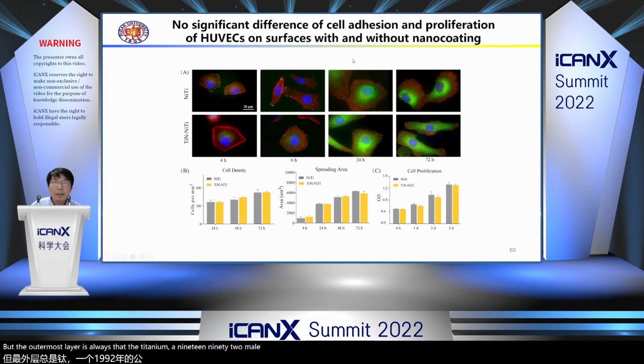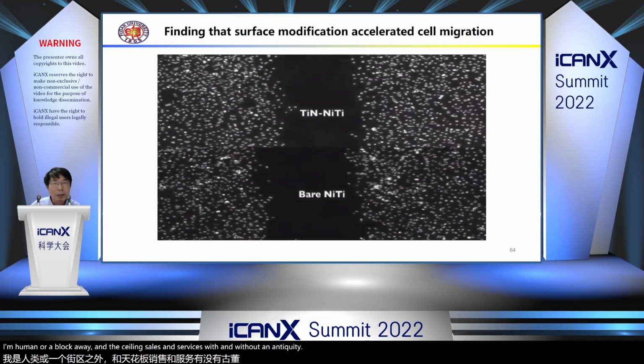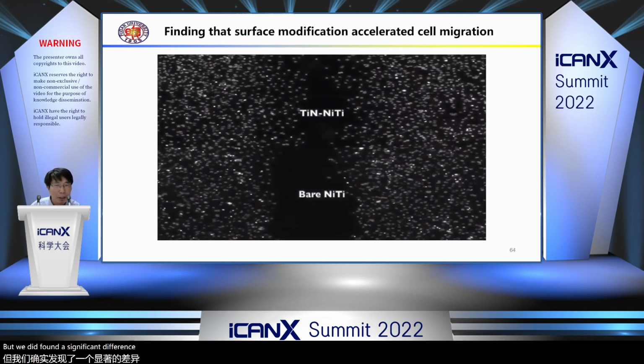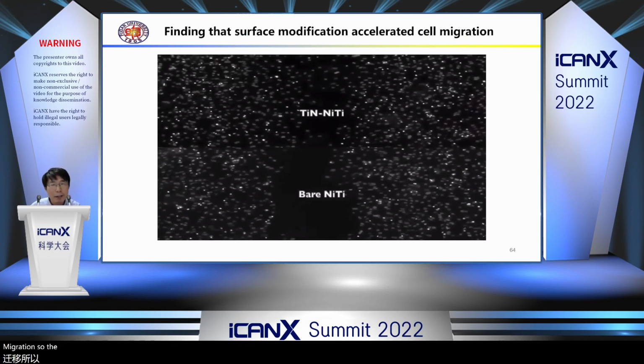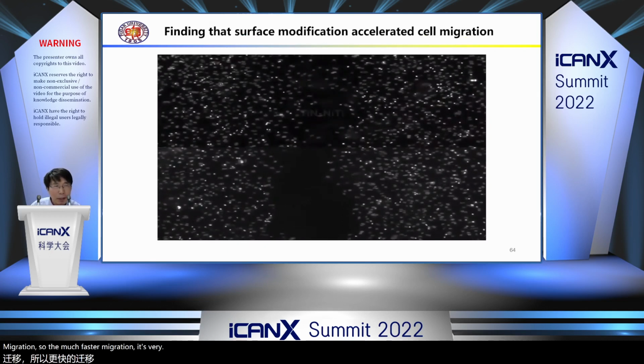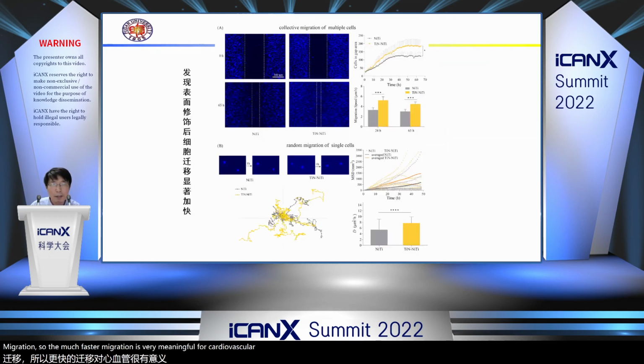And we have not found a significant difference of cell adhesion and proliferation of human umbilical vein endothelial cells on surfaces with and without nano-coating. But we did find a significant difference of cell migration. So the much faster cell migration is very meaningful for cardiovascular implants. We also quantified such behavior to examine the collective migration and the random migration of single cells.